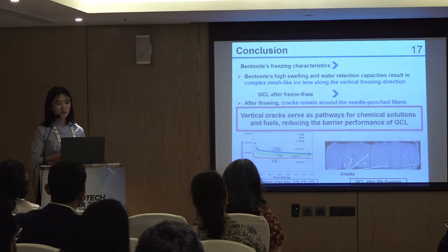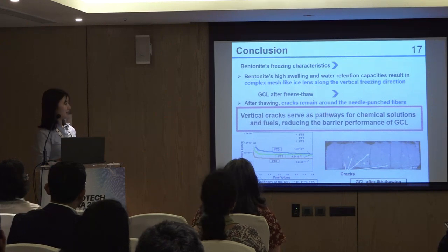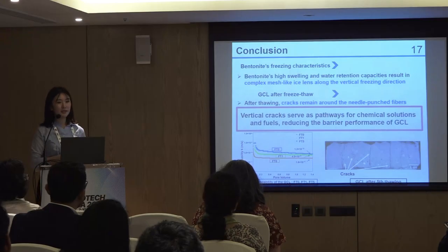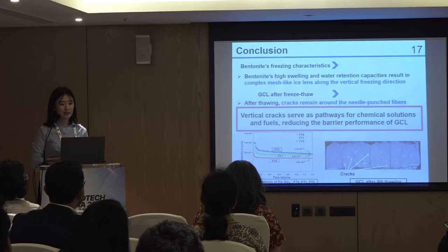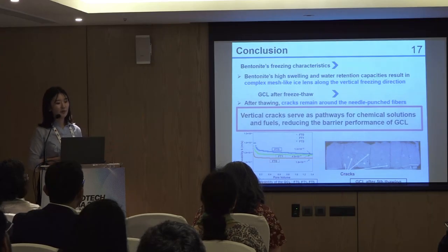Finally, here is a conclusion. When bentonite freezes, ice lenses develop in the vertical freezing direction. This unique characteristic of bentonite remains as vertical cracks in GCL after the freeze and thaw cycles, which could provide a pathway for fuels and other chemical solutions.